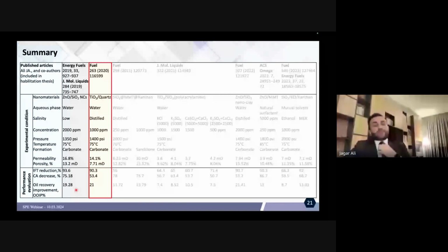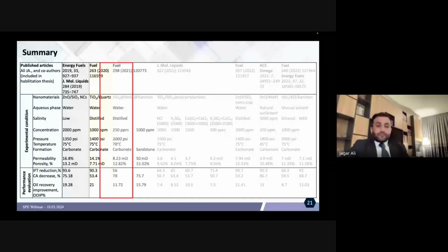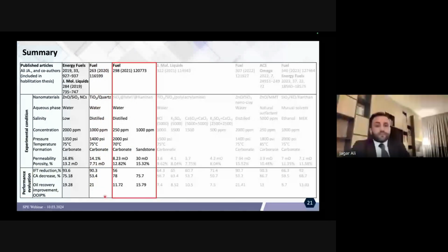And the second work, which was published by Fuel, was the effect of TiO2 quartz with distilled water. We have a good performance in terms of IFT reduction, 90%, contact angle decrease, about 53%, and oil recovery, which is around 21%, which is good. And the third one is the effect of SiO2 montmorillonite xanthan with distilled water. The recovery factor was not good, and even the IFT reduction was not good, but the contact angle reduction was high, around 78%. It was more effective with sandstone rock compared with the carbonate rock, which is around 16% of additional oil recovery.